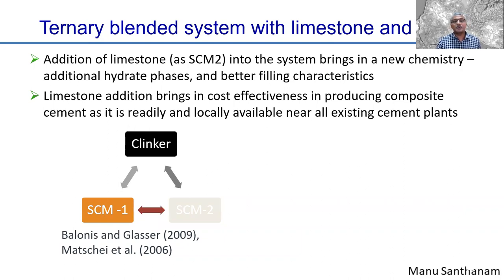So what happens when limestone combines with another supplementary material? For instance, here in the system, you have cement clinker, which is basically all the compounds of cement, C3S, C2S, C3A, and C4AF. You have SCM1, supplementary cementing material 1, which could be your fly ash or slag or calcined clay and things like that. And SCM2 is limestone. So now you have a ternary blend and you get a different chemistry here.